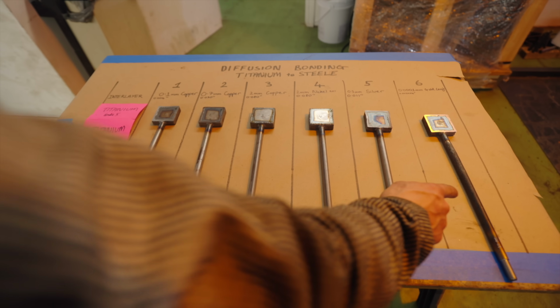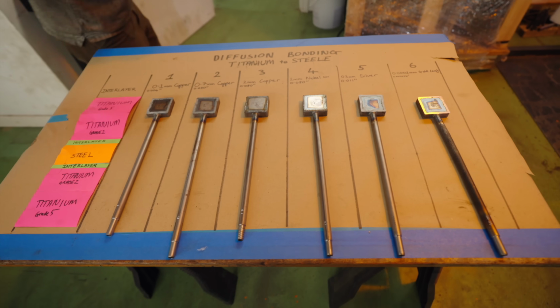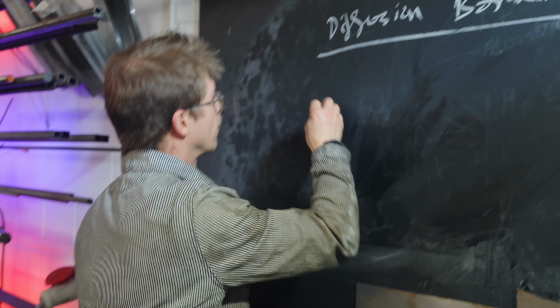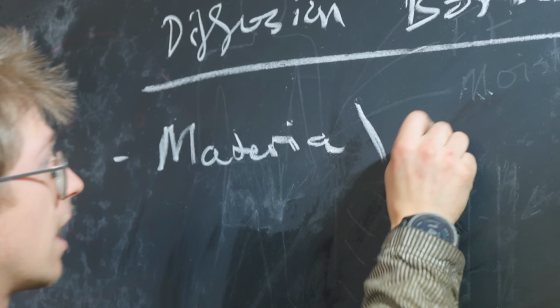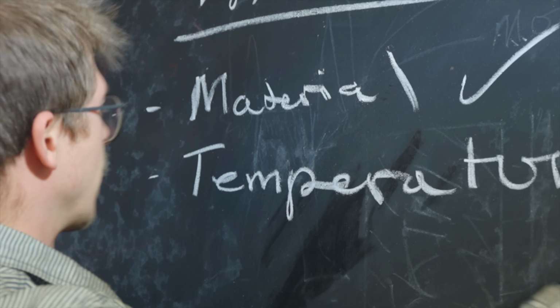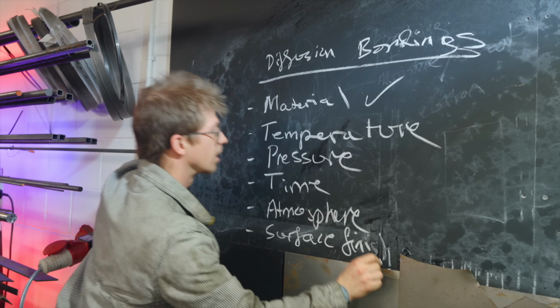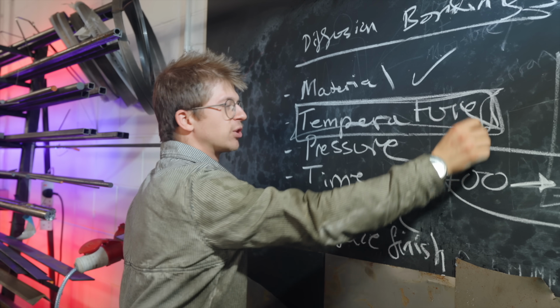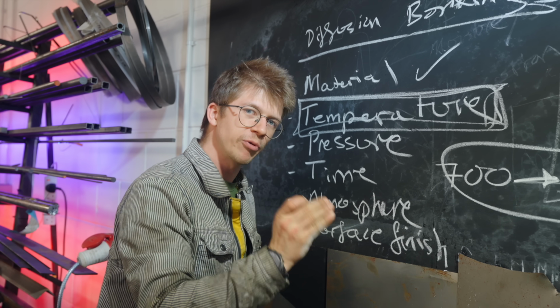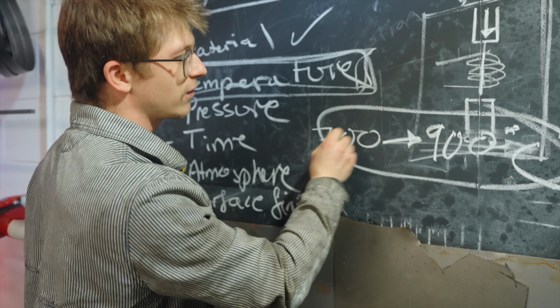They are all ready to go in the forge, but what are the key variables in diffusion bonding? Of course, the material. But we've got that covered. That's what we're testing. Temperature, pressure, time, atmosphere, surface finish. Now, on the note of temperature, one of the variables we can control, the research discusses temperatures in the range of 700 to 900. Even though it feels in my belly like it's far too cold, we're gonna try 850 degrees Celsius for this entire batch.